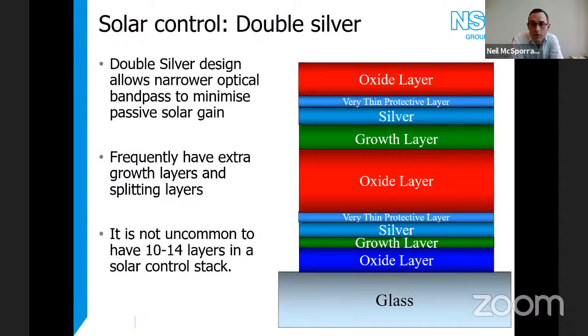And we have different flavors of those depending on the climate and how much solar energy you want to let into the building. But these are very complex materials. A double silver coating can have, well, it says here 10 to 14 layers of material. Actually, some of our double silver materials have around 20 individual layers, with the thinnest layer in the coating even down to about 2 nanometers thick. So we're depositing 2 nanometer thick coatings on a width of 3.2 meters at quite high speed. And yeah, it's a very complex process.